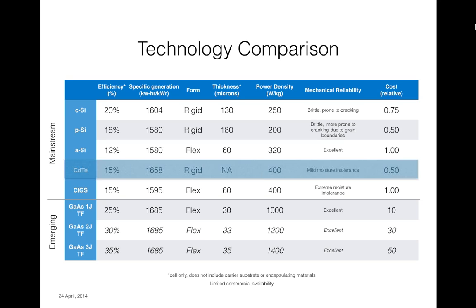However, you still are generating a modest amount of power. 12% efficiency when you put it on an aircraft of a couple meter wingspan is only going to yield about 50 or 60 watts of power. And then, is that really useful or not? That's the challenge. These materials are generally a little bit heavier in that they are on a metal foil of a couple mils in thickness, and so that has some weight to it. And so when you look at the power density, you can get to about 320 or so watts per kilogram using thin film amorphous silicon.